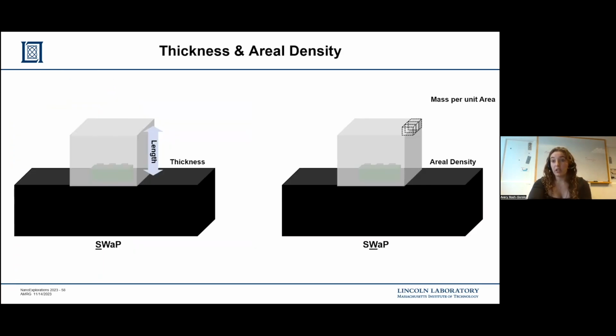When we measure percent radiation block, there are 2 different metrics that we can do this with. The first is thickness. This is when we care about the S, or the size, in SWaP. And it's literally physically how thick off the electronic our shield is. When we use thickness as our metric, the high Z material tends to outperform the low Z material, even if it is an inelastic scattering radiation type.